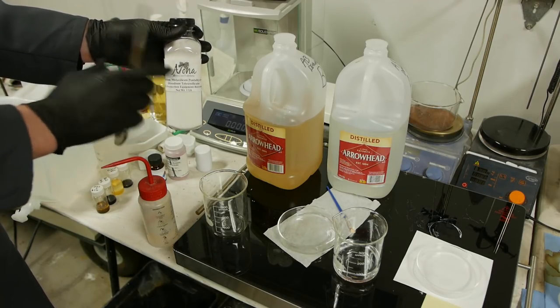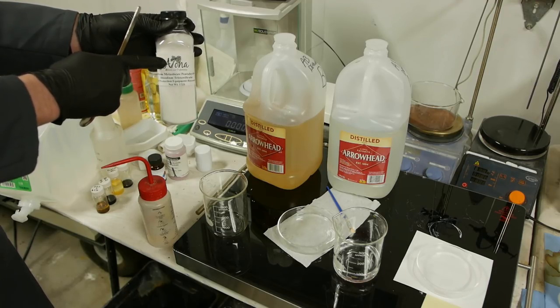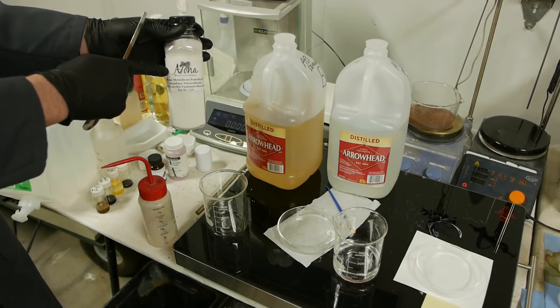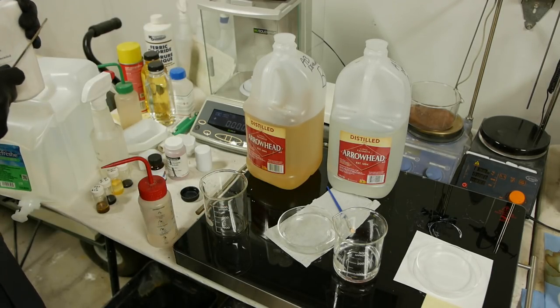And I tend to use three grams per 100 ml of water. And that's it, that's the entire developer. So I'll measure out three grams of this and dump it into the water here. And then we'll develop it in that petri dish.